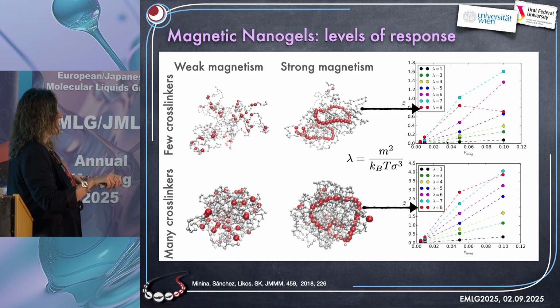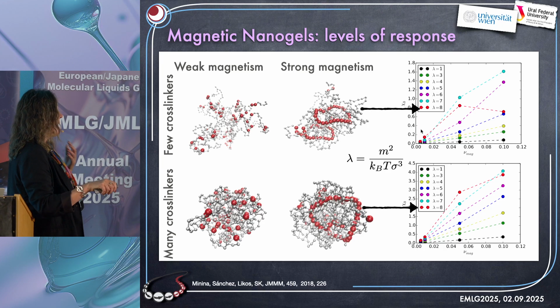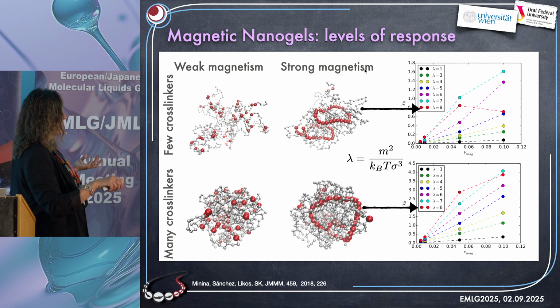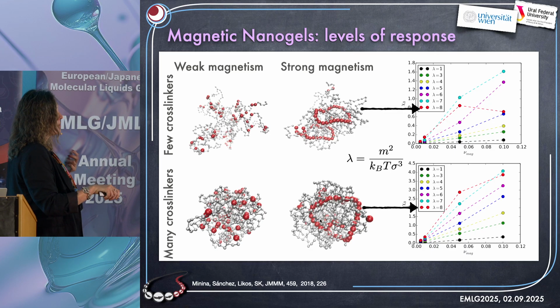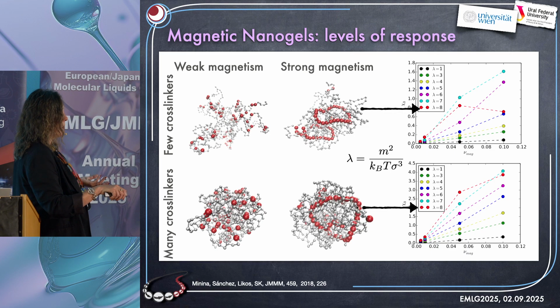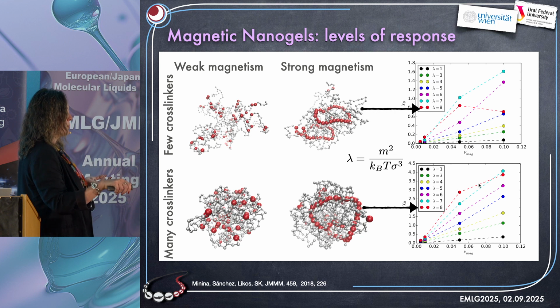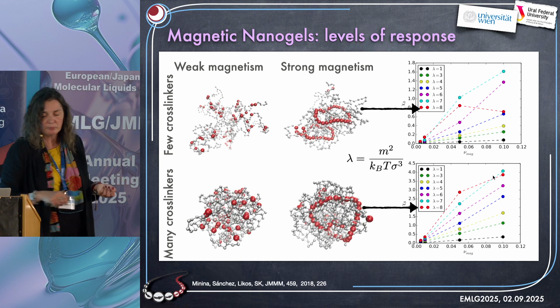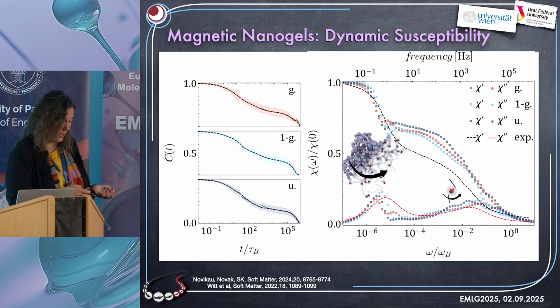And so the static susceptibility for highly interacting particles with a growing quantity of magnetic particles goes down, as for particles not embedded into a gel matrix. But if the cross-linking is strong enough, then the elastic matrix stops particles from aggregating and the susceptibility doesn't really go down. What happens on the dynamic spectrum?